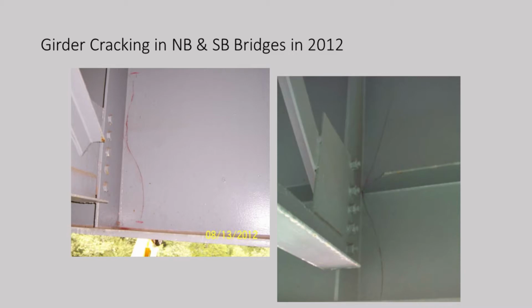Now, this shows the cracking that occurred back in 2012. You're looking at an interior girder from the center section looking outward. And you can see the shape of this crack is kind of unusual. It curves. And usually cracks go straight up and down.